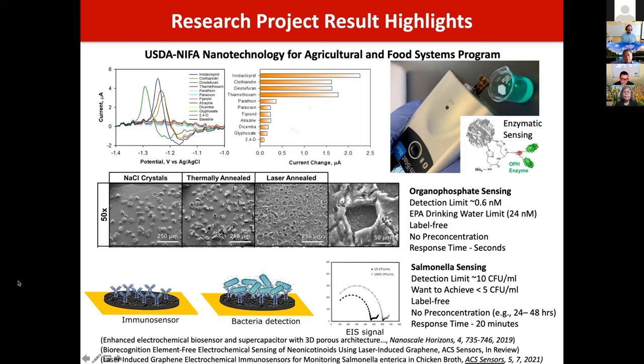And because we have such unique high surface area graphene, we're able to get detection limits down to less than a nanomolar, which is lower than the EPA drinking water limit. So not only could we monitor some of these pesticides in surface waters, but even go back to the drinking water. That's how low we can get. And it's label-free, with no pre-concentration. The response time is in seconds.